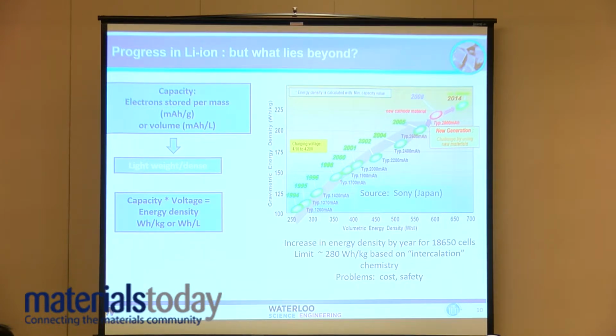But the point is that there has been an increase in energy density year by year for these things that we call 18650 cells, which are like a really big AA battery. But it is generally acknowledged that that limit is about 280 watt-hours per kilogram. And so that's way over here somewhere, but that's about it. This is an asymptotic curve. And so this is the limit for batteries that operate on that intercalation chemistry that I just showed you on the previous slide.